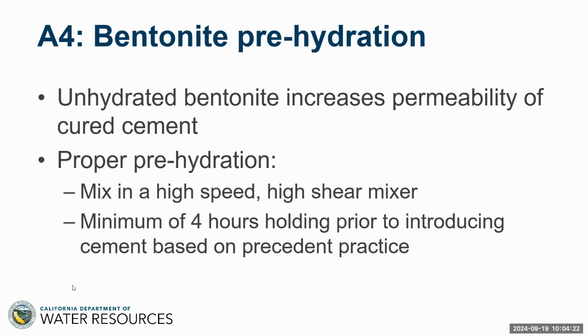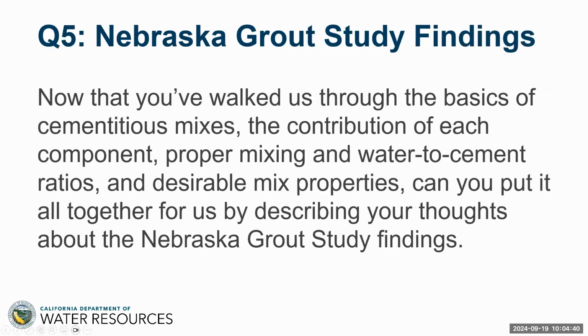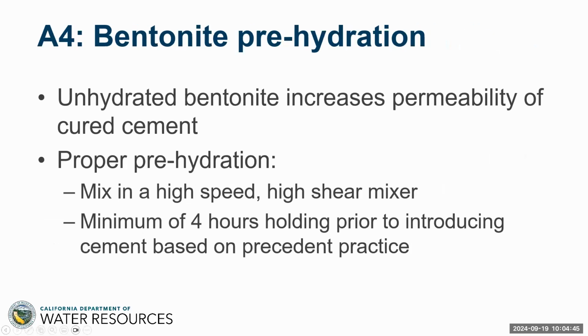And that's based on precedent practice. Different mixer manufacturers will tell you you need 12 hours or you need 6 hours. But Hany, for example, the great Swiss manufacturer, they say that up to 4 hours is more than adequate. So what do we do then? Well, we take the slurry, i.e. the bentonite-water slurry, and then drop it into the mixing tank. And then you add the cement to that, so that the bentonite's already underway, it's already bubbling away, and then the cement reacts in situ there to give a nice balanced grout.